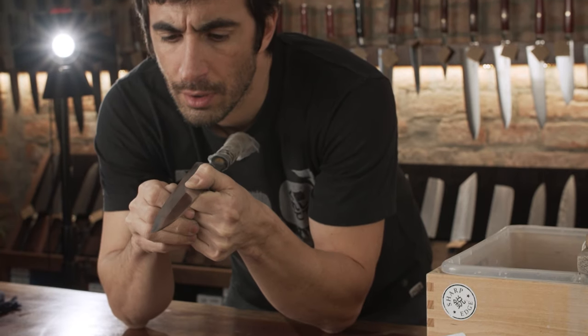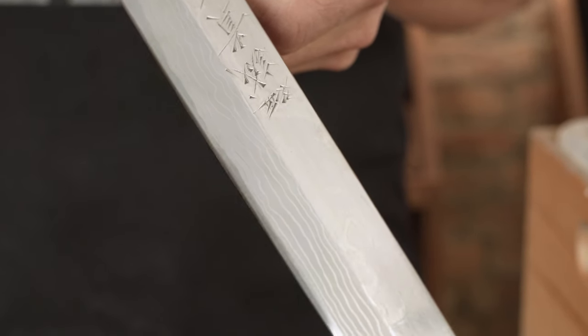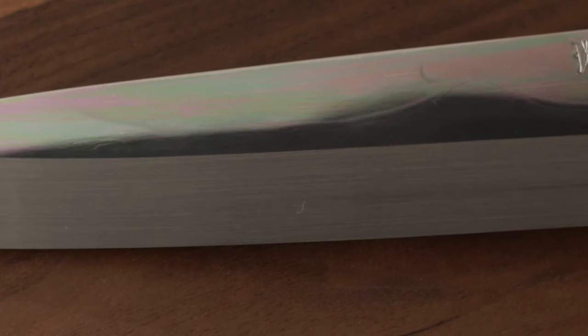We can also continue sharpening on finer grit stones or natural stones. My personal opinion is that all stainless knives are at this stage at more or less 95% of the sharpness of carbon steel knives. Especially Shirogami, where after hardening the steel develops an extremely homogeneous structure with fine small particles, and we can achieve further sharpness on finer stones of 8000 to 10,000 grit. But basically everything over 8000, such as 10,000 grit, is more about the looks than sharpness. If we have a nice Honyaki knife prepared at the highest level, it's considered a traditional Japanese polish following the same techniques as Japanese sword. We can use many different Japanese natural water stones with grits up to 30,000, as well as finger stones. We can then finish with a final step called Nugui, where we take powdered iron oxide mixed with clove oil and rub it with cotton in the Jigane and Hamon area. This procedure makes the Jigane dark and the Hamon line shiny white.